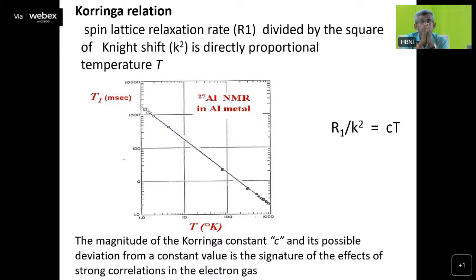So if you know the T1, you can calculate 1 by T1, which is nothing but the R1. Once we know the R1 and the Knight shift, you can plot this as a function of temperature, and you get a parameter called the Curie constant, the Korringa constant. The Korringa constant is a parameter which depends on the electronic density, changes in the free electron distribution, or the interaction within the free electrons, etc.